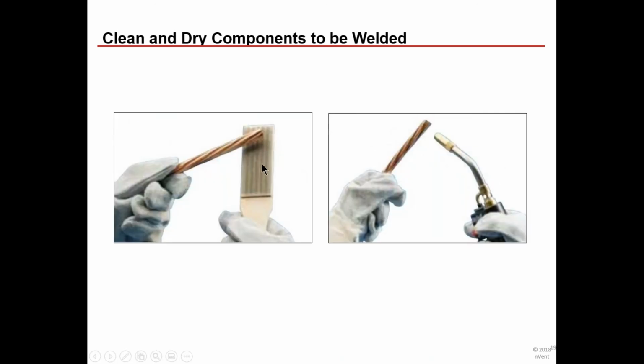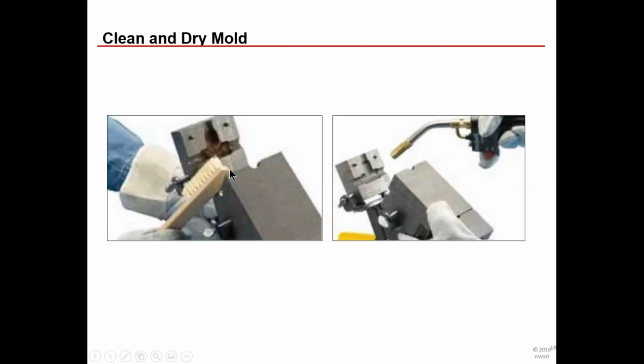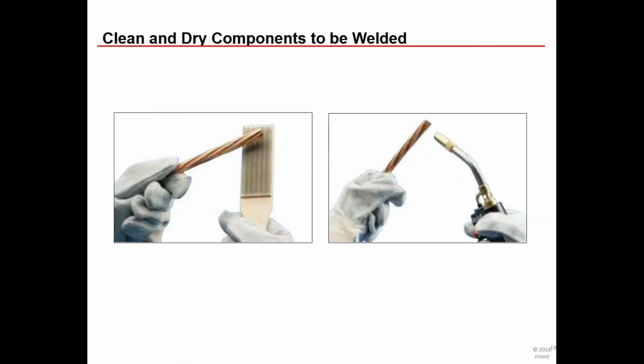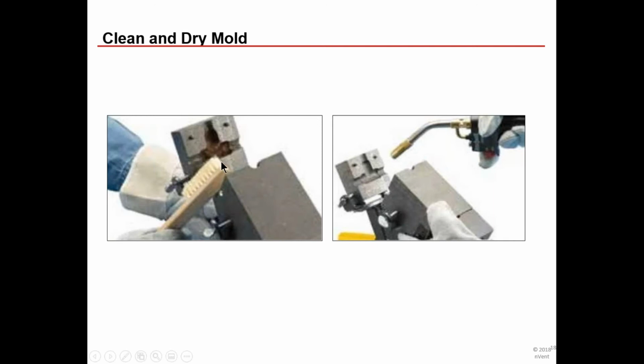Now, one thing, when cleaning the mold, you want to use a soft kind of horsehair type brush. Do not use a wire brush. It will scratch up the graphite and will deform the weld cavity. So it's imperative that you use a softer brush. Erico has those. It's like a medium hair brush, and it's stiff enough that it can get the excess slag and different things like that out, but it doesn't ruin your mold.